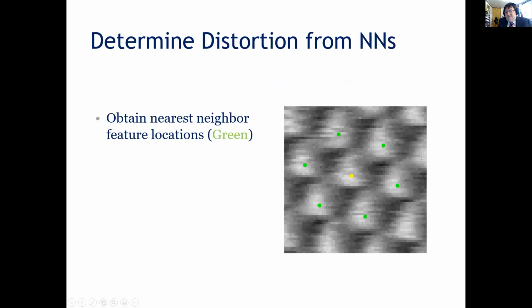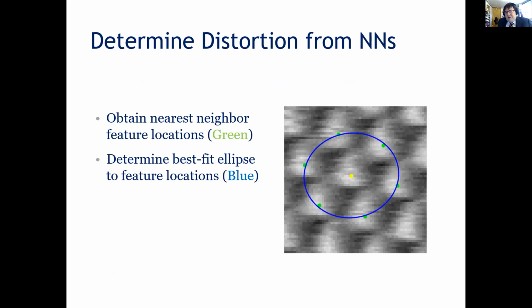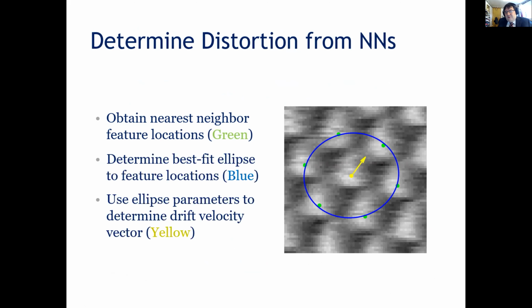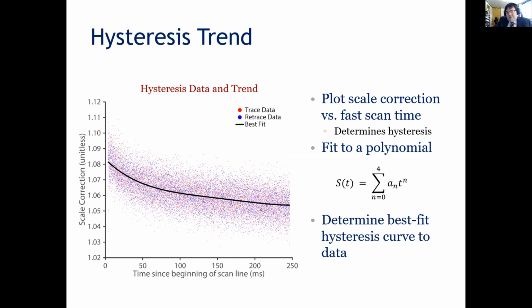So once we have feature locations, here's an example of how we would calculate the distortion. We want to calculate the distortion at this yellow point. So we get the nearest neighbor features in green. We find the best fit ellipse to them, which should be a circle in an undistorted image, but it's an ellipse because the image is distorted. We calculate the distortion that would cause a circle to become this ellipse, and we label the distortion at that point by just that drift velocity vector.